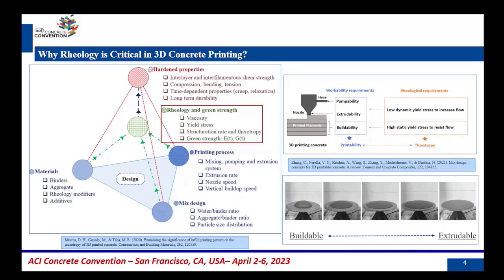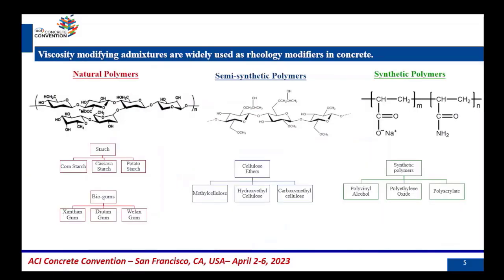If we further talk about 3D printing requirements in terms of rheology, there are very contradictory requirements at each phase of printing. Starting from pumpability, we need a material that has a low dynamic yield stress, so that it is easily pumpable. Similarly, in the extrusion phase, we need a material that has sufficient dynamic yield stress and plastic viscosity, so it doesn't block the nozzle. And right after the material leaves the nozzle onto the printing bed, the whole scenario changes. We now need a material that has high static yield stress and high thixotropy, so that it can sustain the load of the layers on top of the bottom layer.